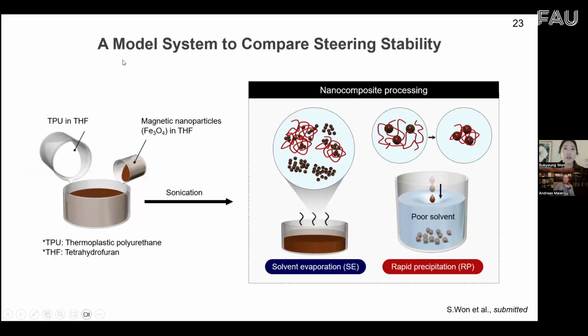So to compare the different nanoparticle mixing states, we implement two nanocomposite processes to compare the distributed mixing of the nanoparticles. For this solvent evaporation case, nanoparticles can easily aggregate due to their high interparticle interactions. So the increased-diameter aggregated clusters sediment at the bottom of the nanocomposite films due to the high gravitational forces in the composite mixtures.